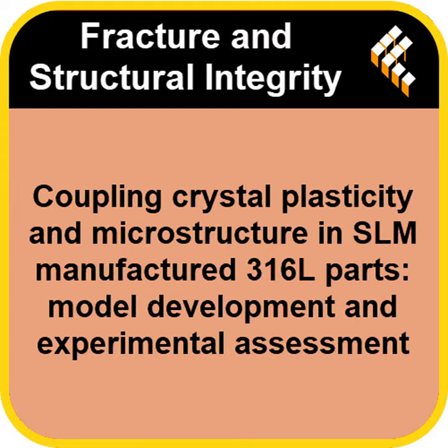Chemically, it's what you'd expect. It's mostly gamma austenite, which is the stable structure for stainless steel. There is a tiny bit of delta ferrite, but the real difference isn't the chemistry, it's the physical arrangement, the grain morphology. So not the nice uniform crystals we might see in a forged part. Not at all. You get what's called a coarse columnar structure. Columnar? Yeah, imagine these really large, elongated grains of iron. They grow directionally, straight up, across the layer boundaries. That's because the heat from the laser is flowing downward so rapidly, and it just pulls the crystal growth along with it. Like skyscrapers growing inside the metal.